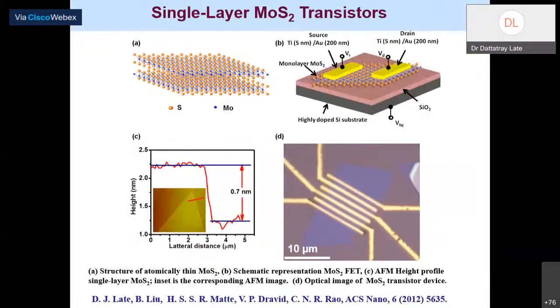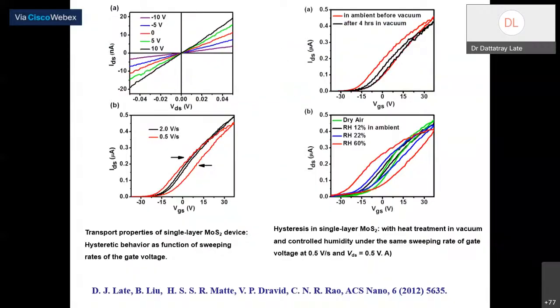So that's the experiment which we have done here. We have made different kinds of devices, again using electron beam lithography, measured the properties of the devices and found out the origin of the hysteresis. We have done an experiment with vacuum. Okay, can you remove a lot of oxygen molecules and water molecules? Yes, we can remove them.